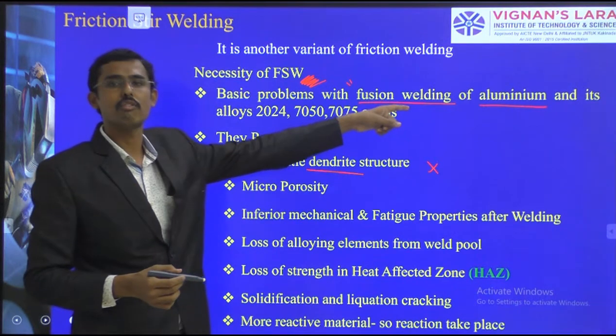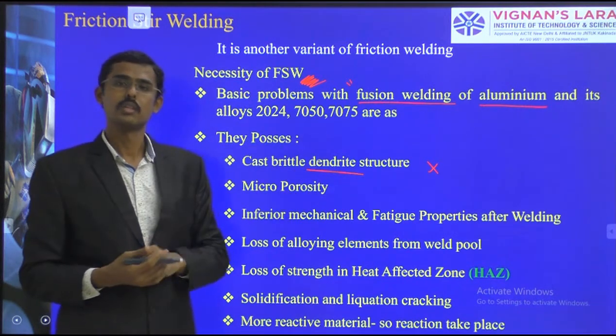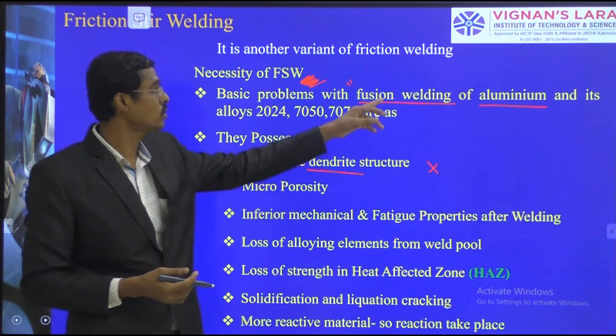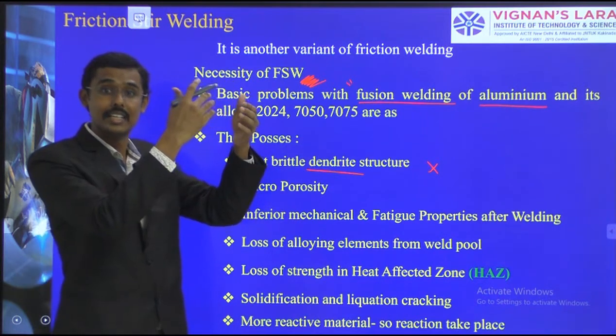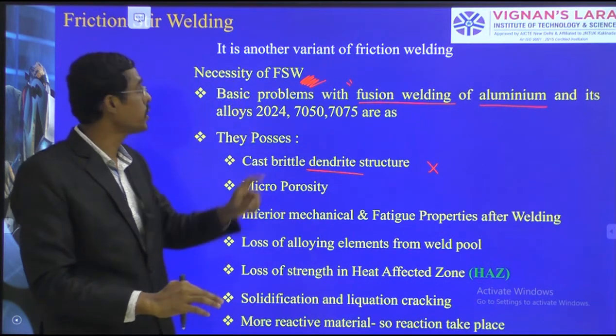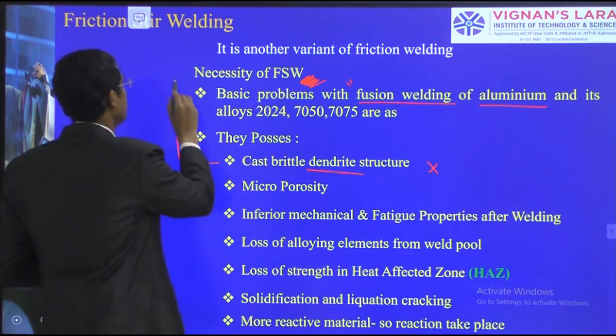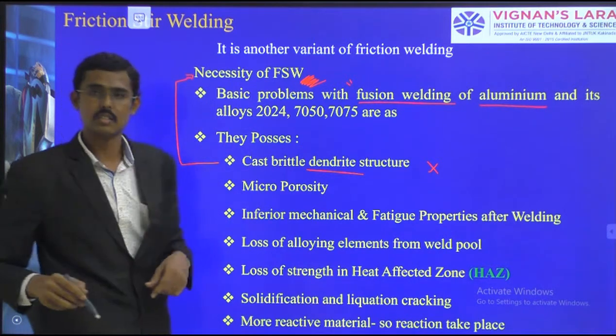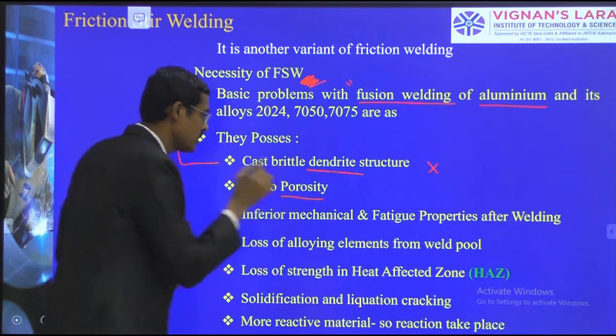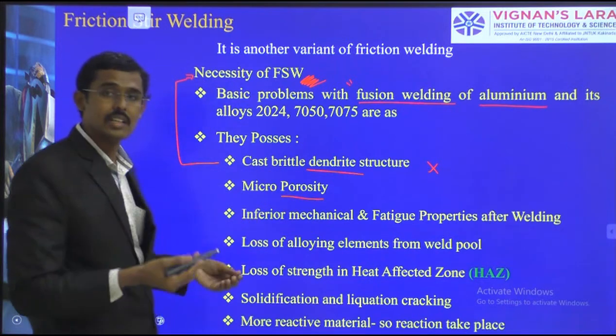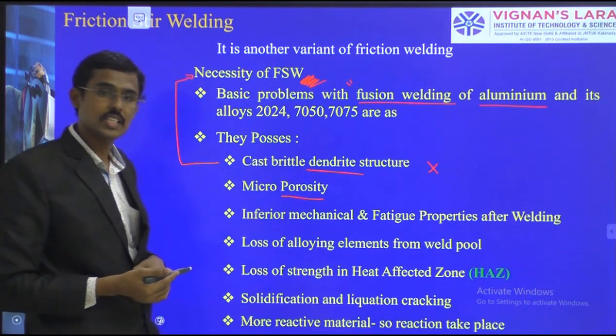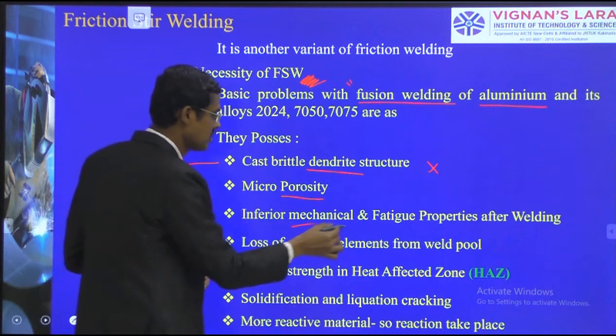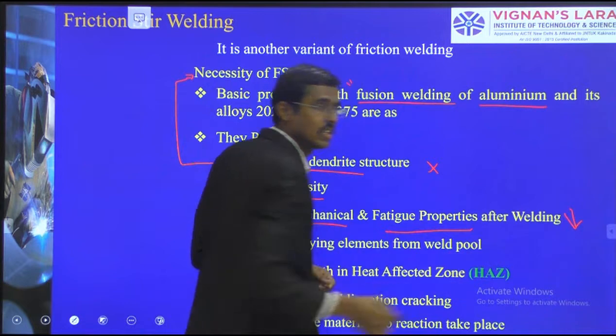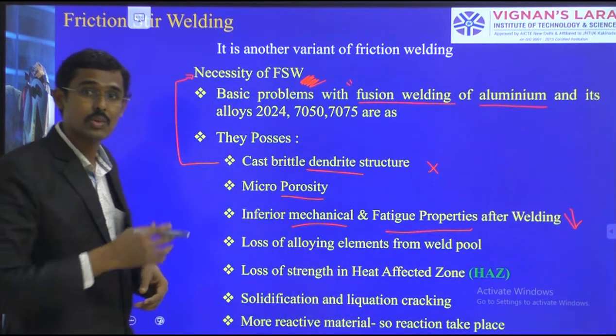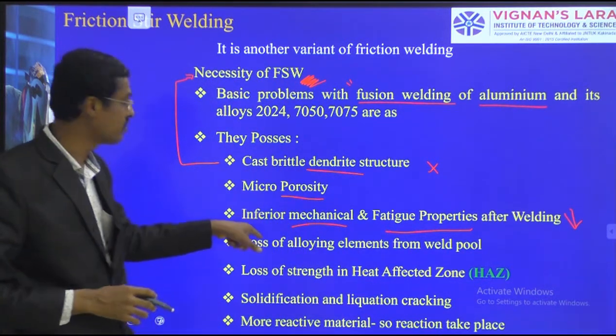In the fusion welding of aluminium, the dendrite forms. It should not form, so we should not do fusion welding at high temperature. The temperature we should reduce. That is why we are going for friction stir welding methods. Then it forms porosities, and due to the dendrite structures the mechanical properties and fatigue properties after welding are reduced. We need more strength compared to the base material, but here it is inferior.